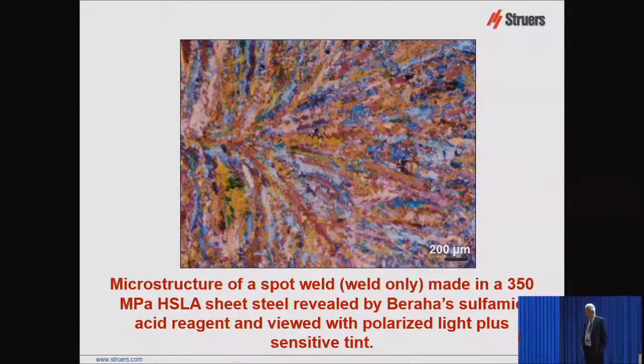Now here's a spot weld in a 350 megapascal HSLA (high strength low alloy) sheet steel. I'm using Beraha's sulfamic acid reagent number one. Not long before he died, he was a relatively young man when he died in '76, he published four different formulas for color etching using sulfamic acid. And they do work very well.